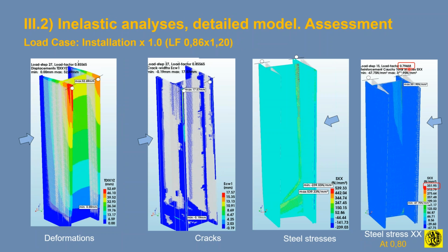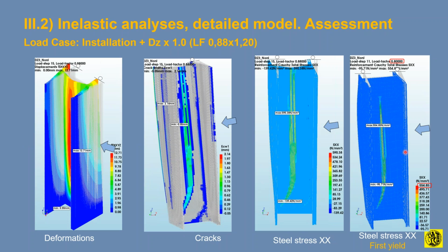If we look at the same load factor here, 80%, where this is only installation stresses and forces, yielding here would not have happened. We would be already at 350 megapascals in this area, actually much less, because there is no differential. Therefore, the stresses here were pretty much elastic. So this would be the case of the installation phase without any breaching of the chamber, which happened more or less in the caisson which was submerged a month ahead, assuming the maturity was the same, because maturity was better in that caisson because the water was warmer. So pretty much this concludes the forensic part of the study.